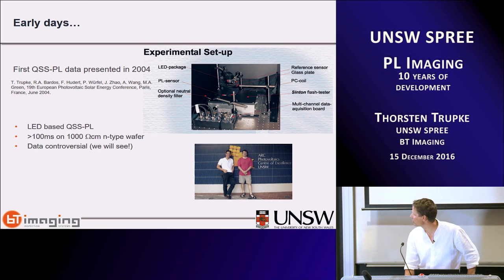So you can see here a very young looking Robert Bardos and I, who started QSSPL work around 2002, 2003. And this is the first setup that we built here in the labs. Back then it was in the old electrical engineering building. We had a QSSPC setup from Ron Sinton, and we modified it to have a photoluminescence sensor. We also replaced the flash with a high intensity LED source, added a couple of filters and a reference diode, and replaced the fairly old-fashioned data acquisition system with a state-of-the-art multi-channel data acquisition board. This system was used to get the first injection-dependent QSSPL lifetime data.